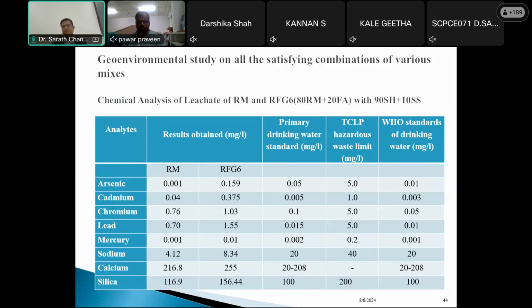Actually, initially we tried to collect the leachate using a permeability apparatus, but because of the fine particle size, we didn't collect any leachate even after a week. We just got 1 or 2 drops. So we decided the regular procedure will not work, because generally we collect leachate from sand or municipal waste by keeping it on a permeability setup. But with very fine material, the regular permeability setup will not work. So we referred to research articles and found TCLP is the easiest method, and we followed the TCLP method.